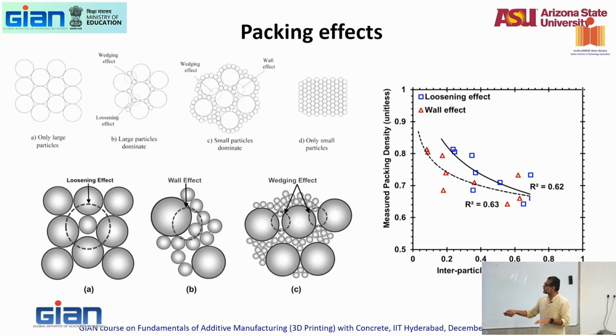So very similarly, you have the loosening effect. Now, if you have all these small particles lining along close to a large particle, there is a wall effect. You remember the interfacial transition zone in your cement hydration story? That's a wall effect basically.